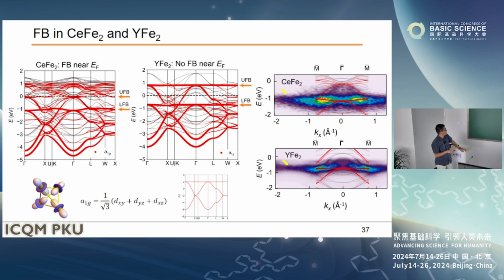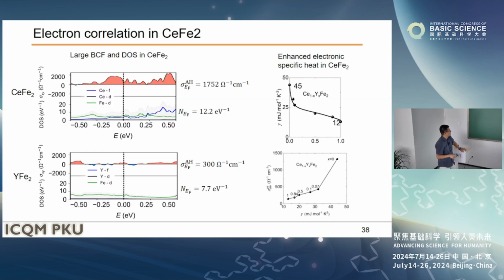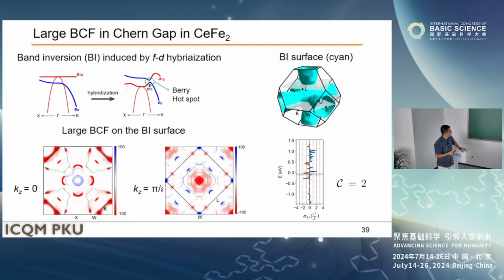So you just lift your Fermi level around the upper flat band. Here you cannot see clearly the upper flat band because it's strongly hybridized with the cerium 4f electrons. And our calculation shows that actually you can see a very strong Berry curvature field and strong density of states for cerium. So here we have an enhanced electron specific heat, meaning the electron mass is much enhanced in cerium iron 2. And also we have a very large anomalous Hall conductivity.